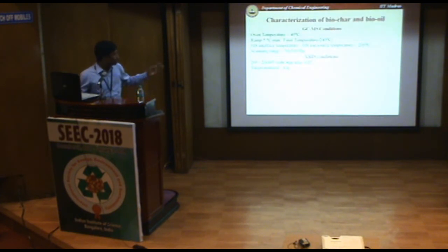And this is the basic feedstock characterization. You can see that KTPP coal is sourced from the Singareni coal field, which is located in Telangana. NCTPS is North Chennai Thermal Power Station, whose coal is mined from the Mahanadi coal fields. You can see the ash content, one is at 18.7, which I named medium ash coal, and the other is 33.4. Of course, there are coals which have around 40% ash also, so that I named high ash coal. The first one is medium ash and the second one is high ash. Experiments were conducted with both coals and the results will be shown here.